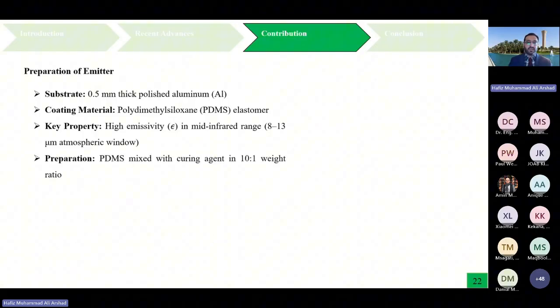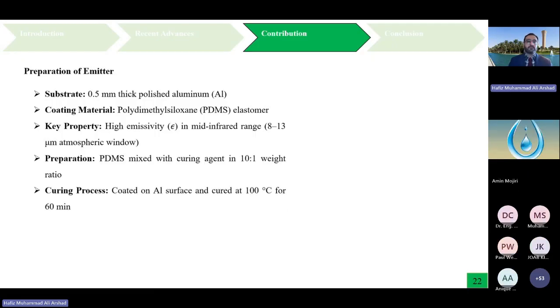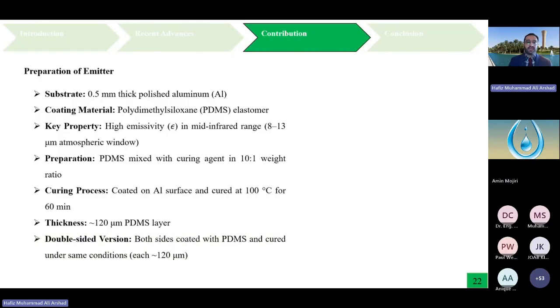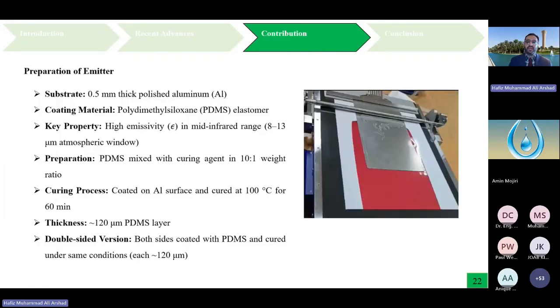This was prepared using PDMS with curing agent in a 10:1 weight ratio. Once we had the coating over the aluminum surface, we cured it at 100 degrees C for 60 minutes. Ultimately, the PDMS layer thickness was up to 120 micrometer. For the double-sided version, we had both sides coated with PDMS and cured under the same condition, each having a 120 micrometer coating. So this is how we create that coating.